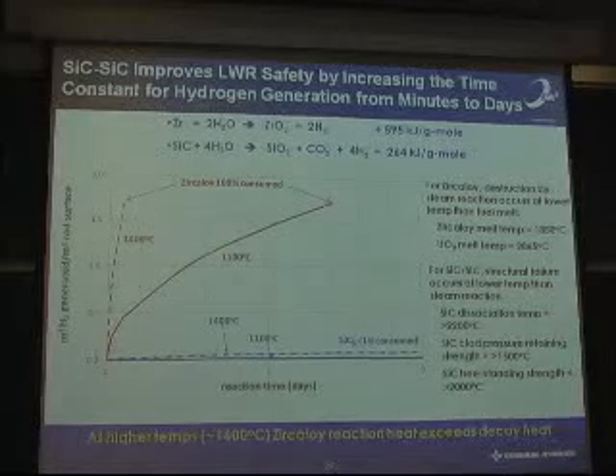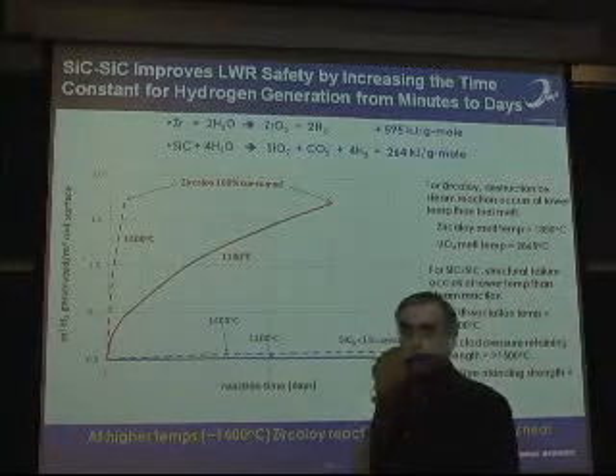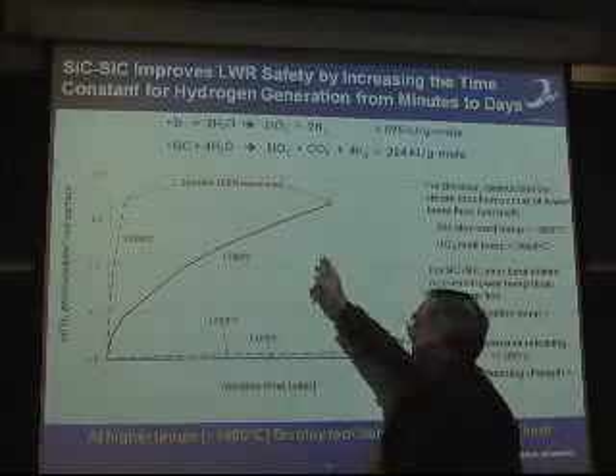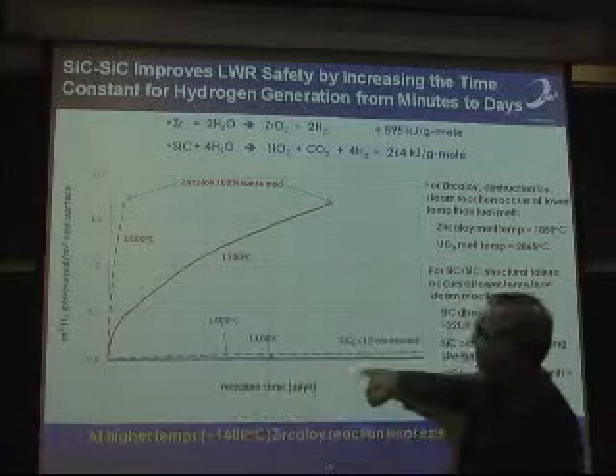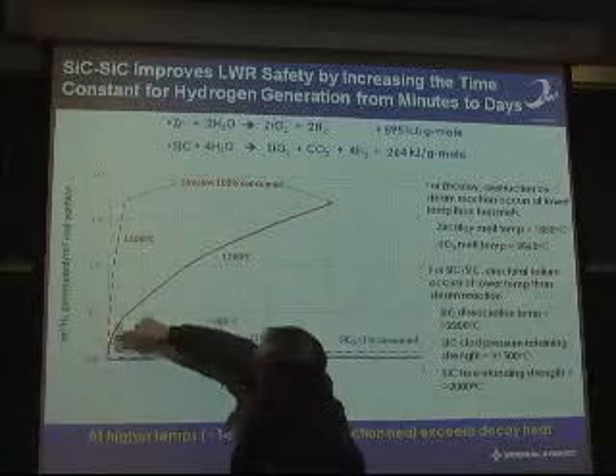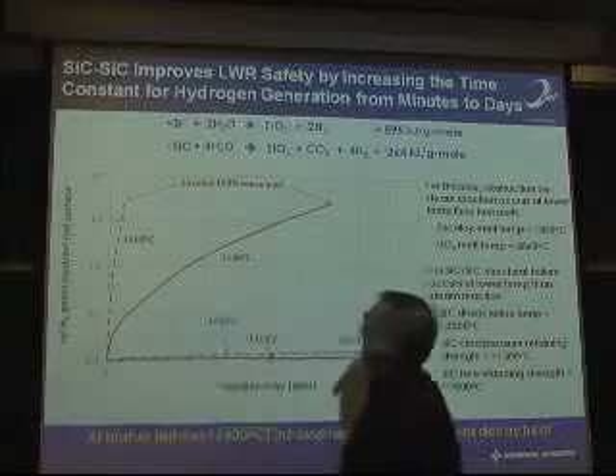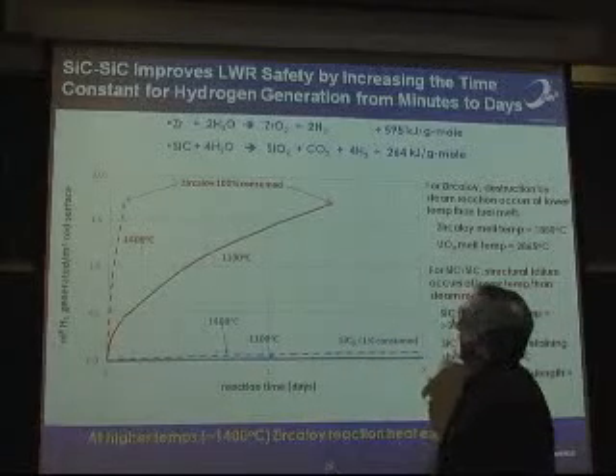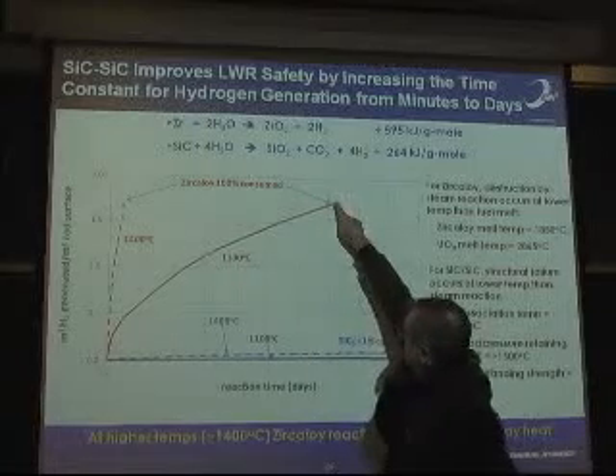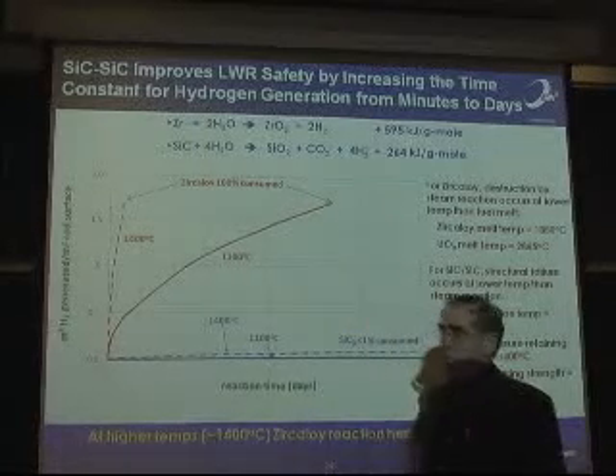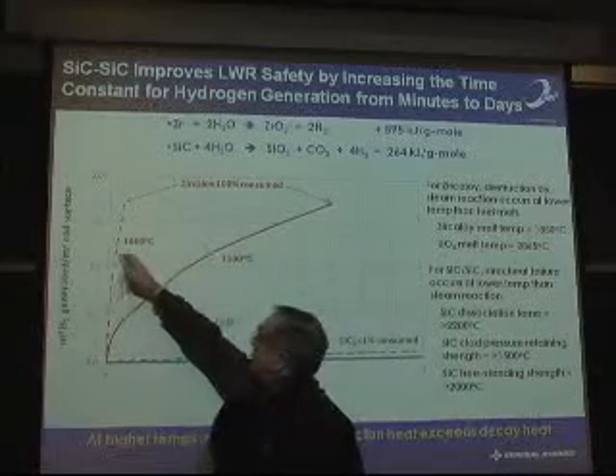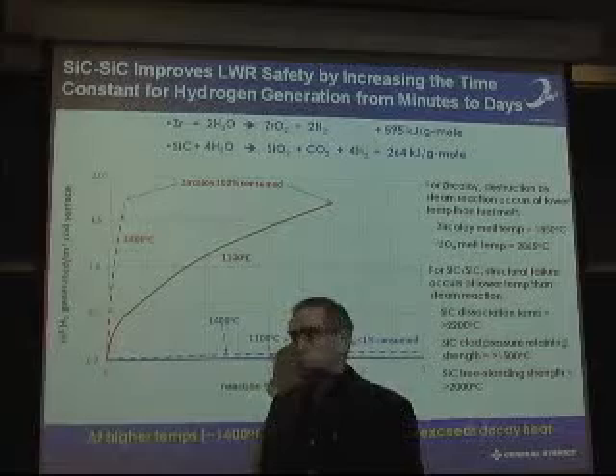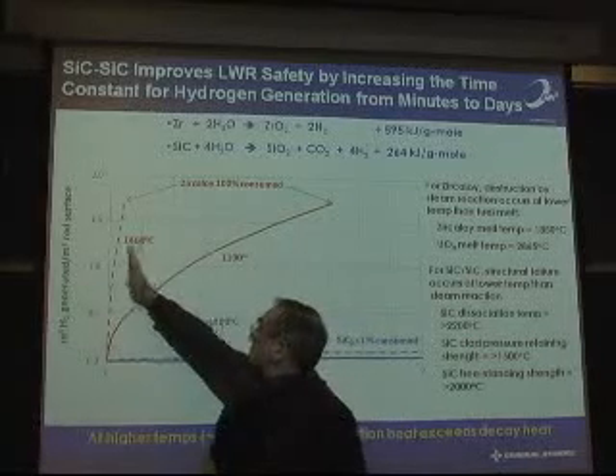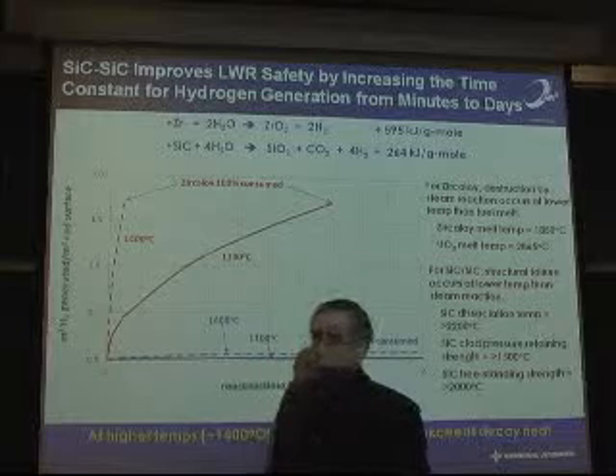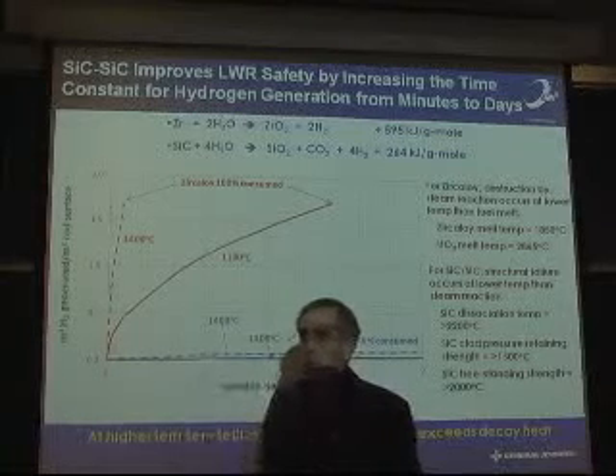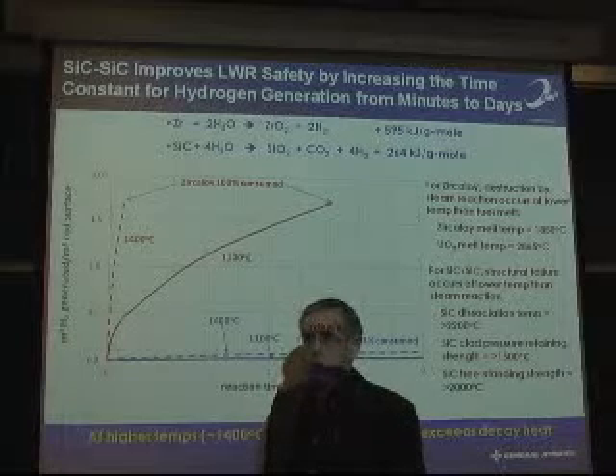What happens in an accident? You know, zircaloy really reacts fast with water. This shows the reaction time in days, and this is the amount of hydrogen generated per meter of rod surface. And at 1100 degrees, basically after about 1.5 days, you've consumed all of the zircaloy. At 1400 degrees C, after about an hour, you've consumed all of the zircaloy. Somewhere in between here, the heat from this reaction outpaces the heat from the afterheat of the reactor, and so it's self-sustaining.